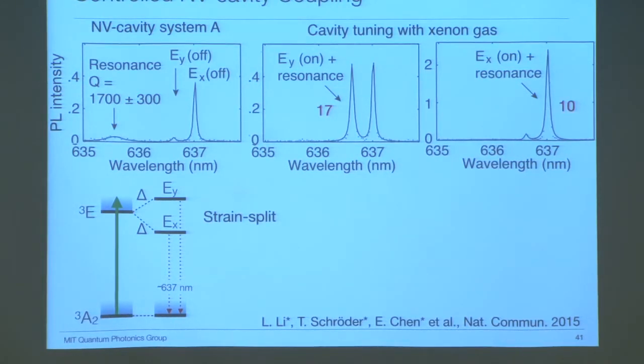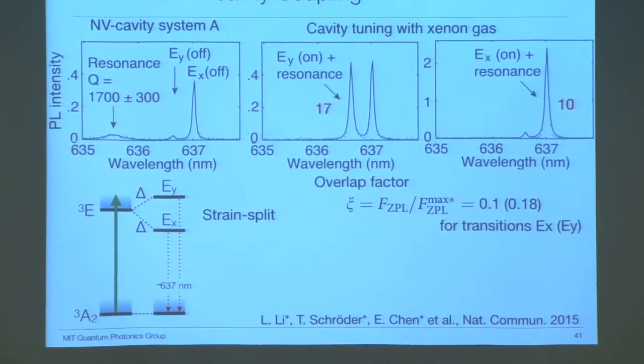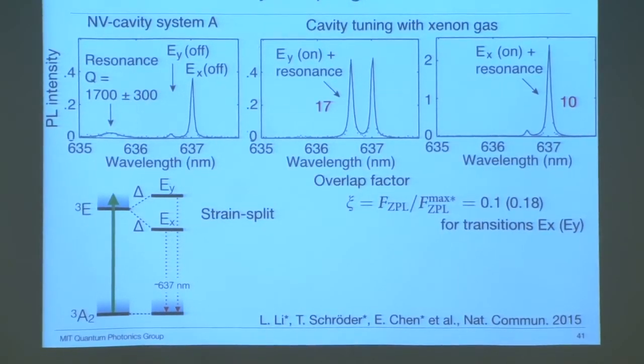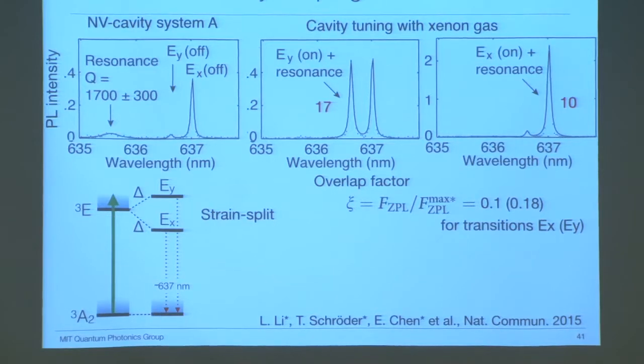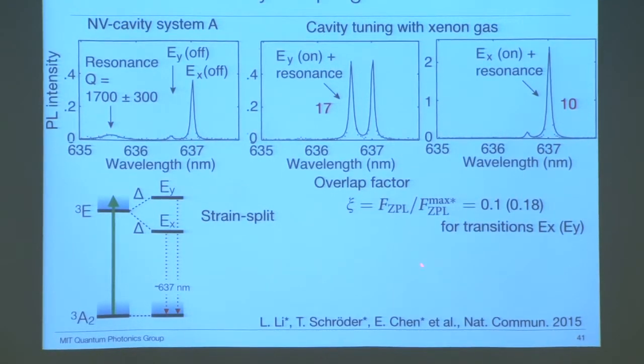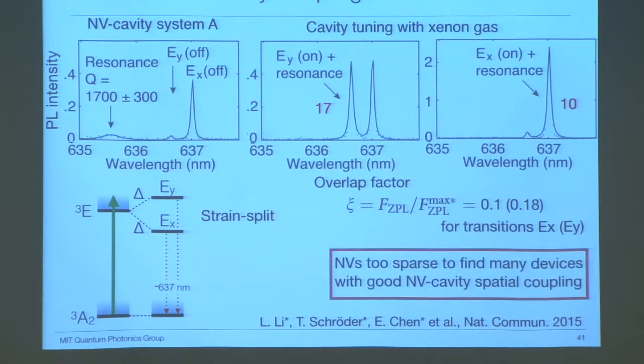And the overlap factor for both transitions is not high. The overlap factor is defined by the experimental Purcell factor over the theoretical Purcell factor. The reason why the overlap factor is not high is because the NVs are too sparse on this sample. It's also difficult for us to find many devices with good NV cavity spatial overlap.